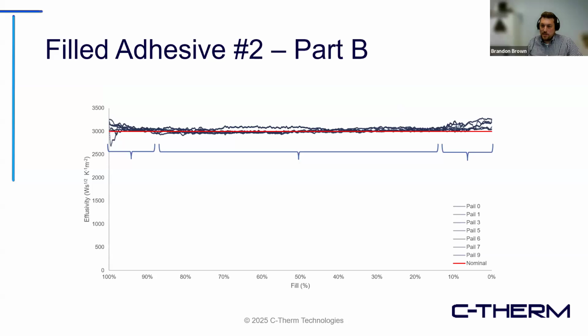So moving to another production line and another filled adhesive, I've overlaid a number of pails here which were processed to show the variance of the second filled adhesive. It had some different properties, different viscosities. Again, this was mounted above the pump in a pipe where all the material processed from their pail would flow through. Here, the red line represents a nominal value. There wasn't enough information in the data sheet to directly calculate the effusivity, but for the purposes of this testing, we were focusing on consistency anyway, so the nominal value was used.